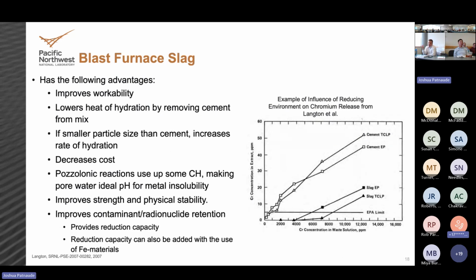What the sulfur does is it provides electrons and a reducing environment, which helps suppress the release of contaminants, in our case radionuclides, by reducing them to a lower oxidation state. So one of the fundamental mechanisms of why saltstone works for low-level waste mobilization at the Savannah River Site is their work in the 1980s to develop the saltstone formulation. The inclusion of blast furnace slag greatly suppressed the release of chromium in their waste, which showed marked improvement in both the TCLP tests, we'll touch on this in a second, and long-term leaching.